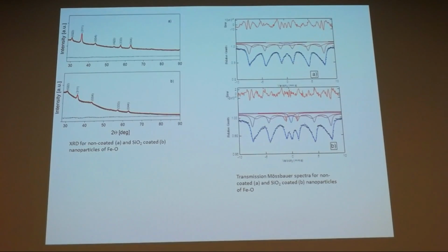And we have done X-ray diffraction for these nanoparticles, and the Rietveld analysis has shown that the nanoparticles had a size of the order of 15 nanometers, and this is a single-phase structure containing only magnetite nanoparticles. For the coated nanoparticles, we have seen the same diffraction peaks. However, there was a lack of peaks coming from the coating, so we assume that the silicon oxide forms an amorphous coating around the nanoparticles.